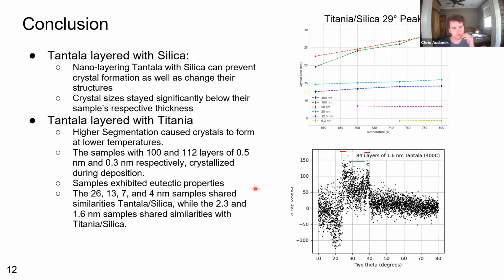So in conclusion, with tantala layered with silica, we saw that nanolayering tantala with silica can prevent crystal formation as well as change their structures. And also that crystal sizes stayed significantly below their sample's respective thickness. So if you look at the graph here, you'll notice that each of these lines is well below the actual layer thickness right around here. You can see here.